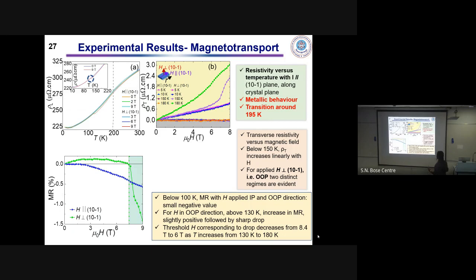However, when the magnetic field is applied in the out-of-plane direction, above 130 Kelvin, we have observed that the MR increases and then after a certain field it shows a sharp drop. And this threshold field corresponding to the drop decreases from 8.4 Tesla for 130 Kelvin to 6 Tesla for 180 Kelvin.